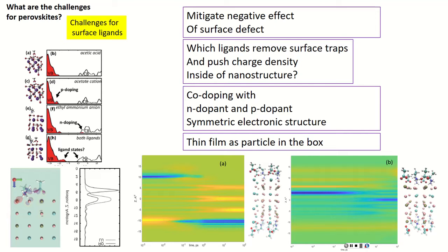Best light emitters are quantum dots. But in simulation, one needs to have surface termination from each side. And sometimes it is easier to study surface effects just on thin films. So this is work of Daniel Ramirez. And he is trying to passivate the surface of cesium lead bromide perovskite by a combination of anions and cations according to standard procedures in literature from the Switzerland group of Maxim Kovalenko. So when one combines both anions and cations, on average the layer of ligand is neutral, has a band gap higher than the natural band gap of perovskite, and prevents the surface from having trap states.